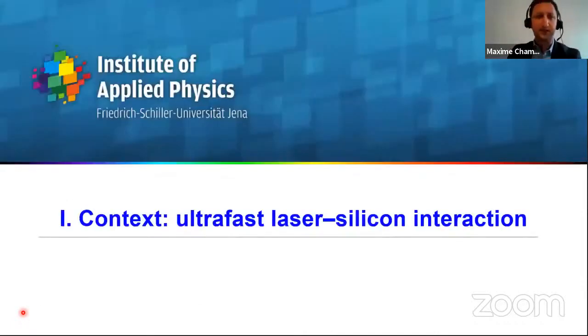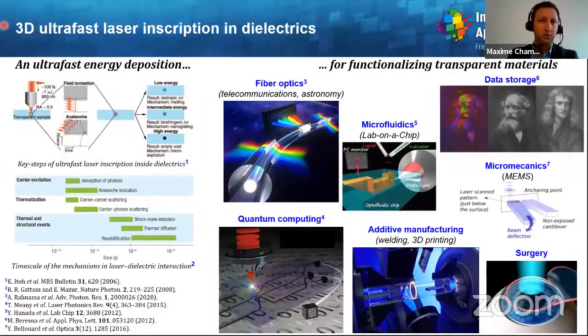So first, let us introduce the context. As you may know, 3D ultrafast laser inscription in dielectrics is a proven technique. And essentially, the reason for this is that at the time scale of 100 femtoseconds, namely ultra short laser pulses, you have an ultrafast energy deposition, which means an important thing, which is that you can distinguish and separate the causes, which are essentially the absorption of the photons, from the consequences, which are the material response. And in this case, it's possible to achieve an extremely high degree of control on the modifications you can produce in dielectric materials.